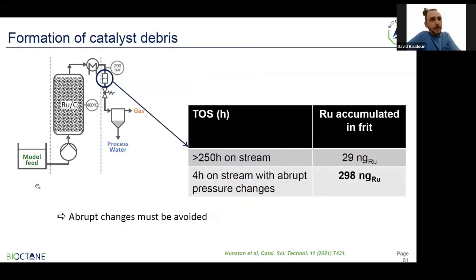Next slide, please. However, we found a huge impact of the pressure, of the process condition. When the process is very smooth, with no fast change of pressure or change of temperature, there is very, very low leaching of ruthenium. And you find here an example: after 250 hours on stream, in the frit that is downstream of the reactor, protecting the back pressure regulator, we found a very small amount, 29 nanograms of ruthenium. And after 4 hours of a test with on-purpose abrupt changes of pressure, not that abrupt, but changes that can be observed